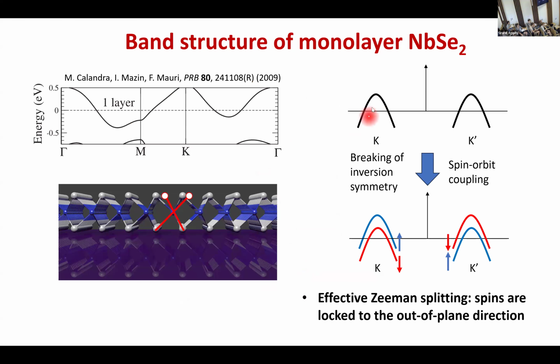And for this band around the K and K prime points, now I'm drawing this around K and K prime points. I mentioned before that this crystalline structure lacks inversion symmetry, which means, not really like for the Rashba effect, we have this mirror symmetry thing. So here is the central symmetry. If I draw a line connecting one selenium atom to the other side, you see that this empty circle cannot match with the real position of selenium.